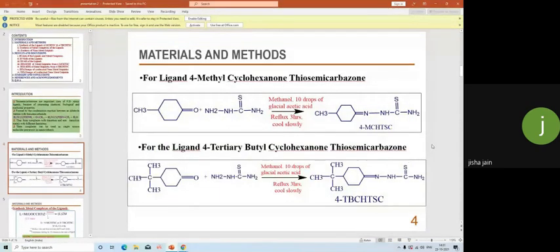Then materials and methods. First, the ligand 4-methyl cyclohexanone thiosemicarbazone. For that, equimolar methanolic solutions of 4-methyl cyclohexanone and thiosemicarbazide along with 10 drops of glacial acetic acid are refluxed for 3 hours and then cooled slowly. The 4-methyl cyclohexanone thiosemicarbazone gets precipitated. Then for the second ligand, 4-tertiary butyl cyclohexanone thiosemicarbazone, 4-tertiary butyl cyclohexanone and thiosemicarbazide are taken as equimolar methanolic solutions and refluxed on a water bath for 3 hours along with 10 drops of glacial acetic acid and then cooled slowly. The corresponding compound, 4-tertiary butyl cyclohexanone thiosemicarbazone, gets precipitated.